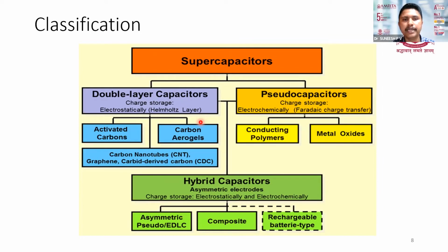And in order to fabricate double layer capacitors, mainly we are using carbonaceous materials: activated carbon, carbon aerogel, carbon nanotubes, graphene. All these materials have high surface area, and thereby they can allow the adsorption of more ions on the surface, so more charge can be stored.